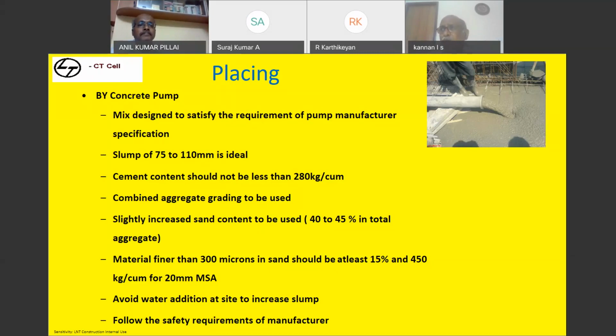If you are able to make a concrete of such kind, your mix will be perfect. So to achieve that, if you have around 40 to 45% of sand in your mix, definitely your concrete will be highly workable. Then material finer than 300 microns in sand should be at least 15%, and 450 kg per cubic meter in a 20 mm aggregate.